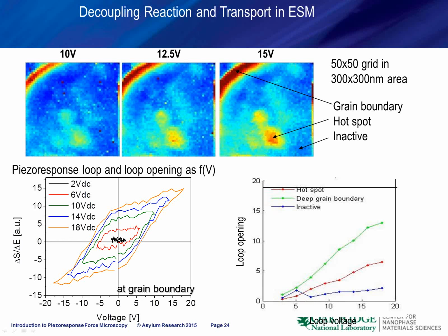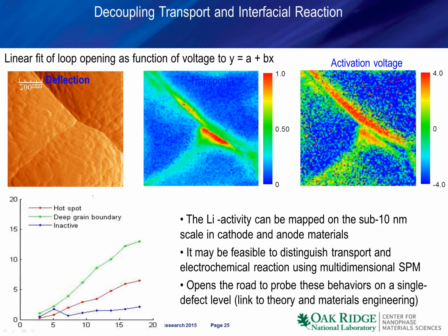We can analyze this using multivariate statistics and show that in the first approximation it is linear behavior. In fact, we can fit all this data at each spatial point by a line. And this is what we get. In this case, we have a topography image. We see the image corresponding to the slope of the voltage behavior of the loop opening, which gives us information about the transport. And we get the image corresponding to the voltage required to activate the electrochemical reaction. And lo and behold, you can see this activation voltage is pretty much the same across the grain boundaries. It's about 4 volts. At the same time, you see a drastic difference in the transport behavior.